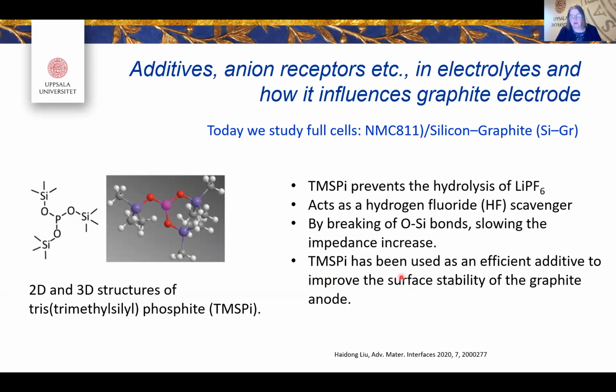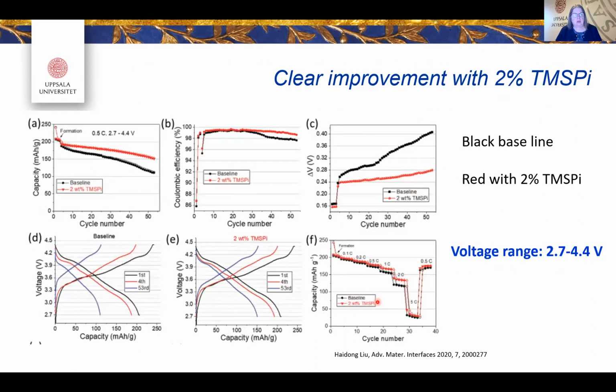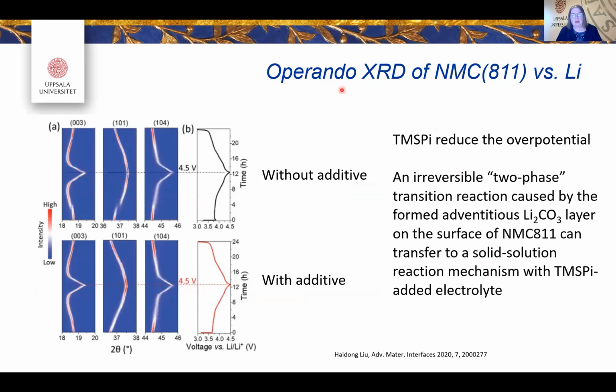And this has not only protected the cathode, but is also an effective additive to improve the surface stability of the graphite anode. So you can see that only a small percentage of the scavenger, this anion receptor, makes a big difference cycling-wise. You have the baseline, and here you have the same, but with TMSPi, you see it's quite an improvement. And it's also nice rate capability test. By operando XRD, we can also see that it actually influences the cathode.